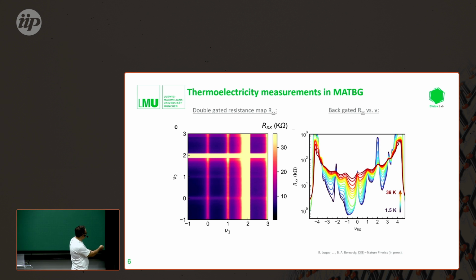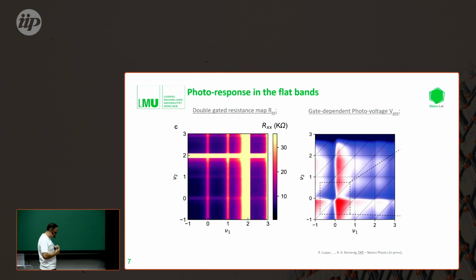And the checkerboard pattern that you can see here is really just tracing all those correlated insulator states in the two different regions. Each of those lines corresponds to one of those peaks, and from the perpendicularity of those lines, we can see that those gating structures are really doing their job and tuning the two different regions separately. Now we can turn on the heating source, shine laser light on it, and read out the photovoltage from the device. You can see that the photovoltage that we read out inherits some of that checkerboard structure, and it oscillates with the same periodicity as this checkerboard.